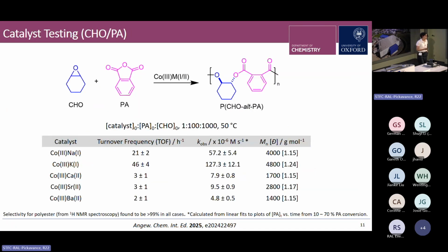So these are the results of the catalyst screening for the copolymerization of CHO and PA. And the first thing to note is that all 5 catalysts are successful at making a polyester with narrow dispersity. So that's indicative of well-controlled polymerization catalysis in each case. However, we can see that there are significant differences in catalytic activity across the series, as quantified by the turnover